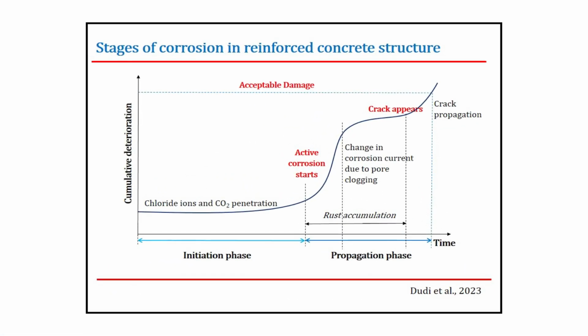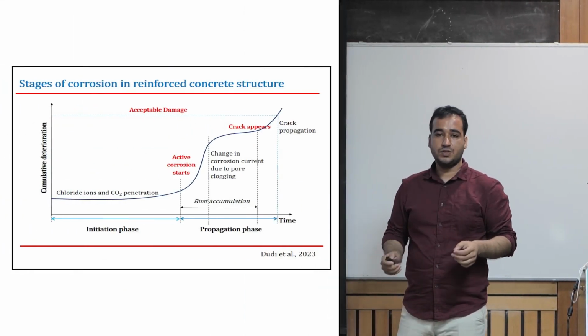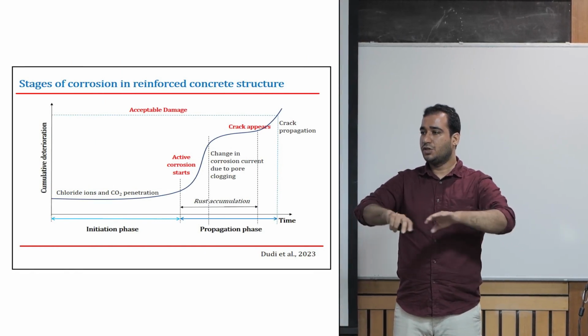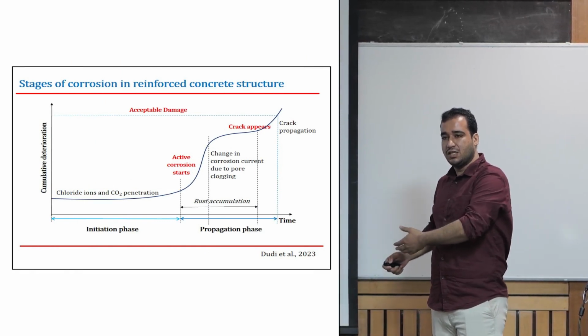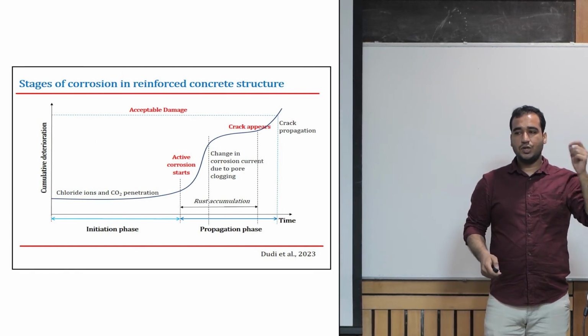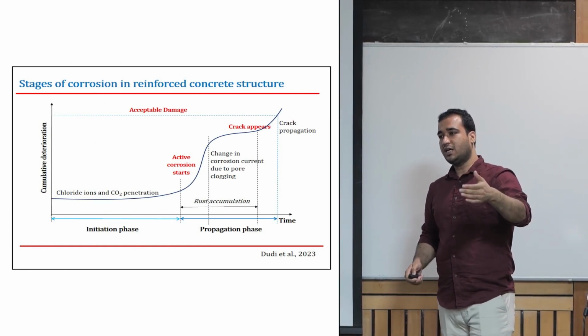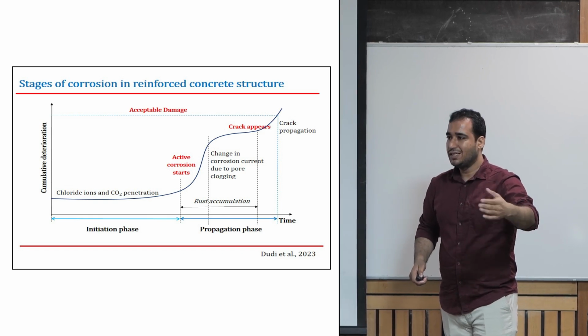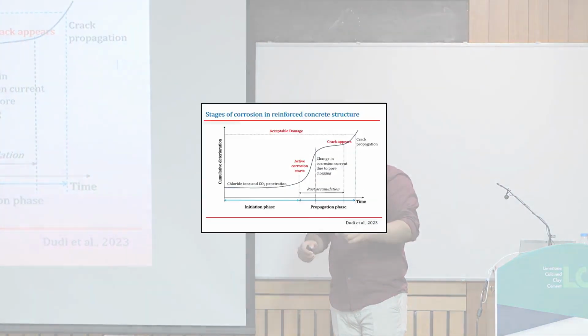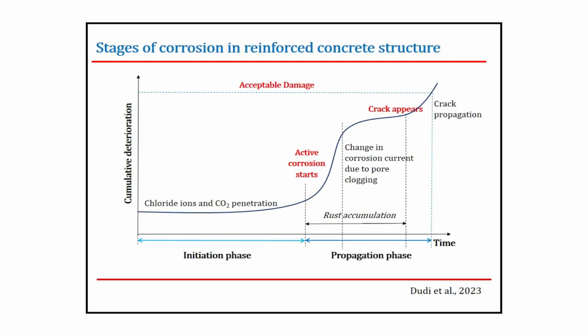So when we talk about corrosion, like one of my friends just said, okay, chlorides. When we say durability issue, it's corrosion. Sometimes we think chlorides and corrosion are different. The thing is, in terms of corrosion, we divide the total life into two stages. One is the initiation stage, another is the propagation stage. The initiation stage is the part where the chlorides or, say, carbon dioxide ingress into the structure and lead to active corrosion. The point where the rebar starts to actively corrode.